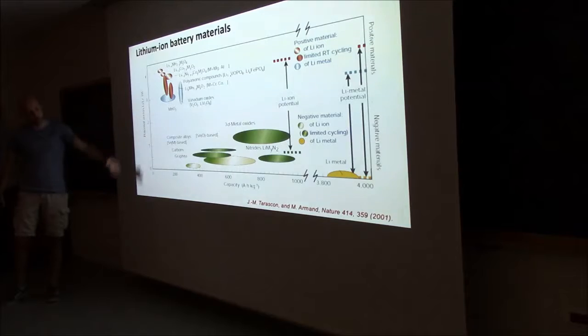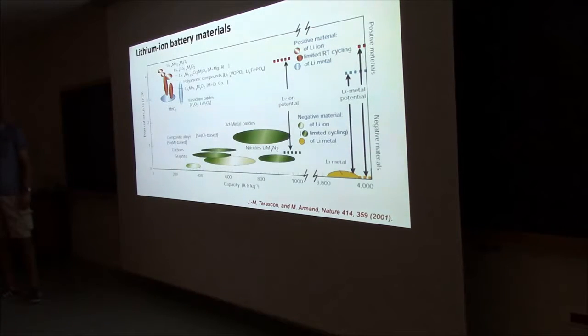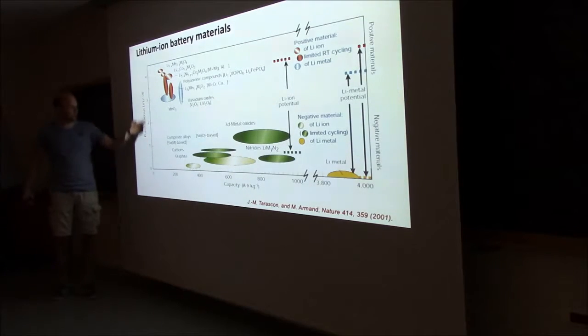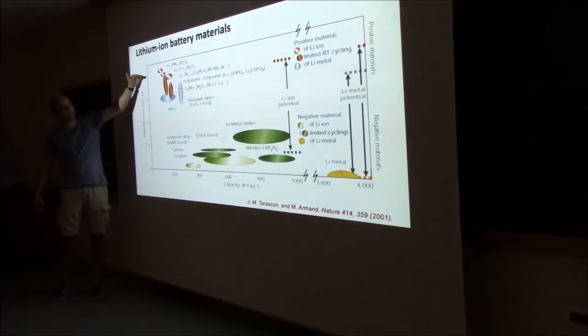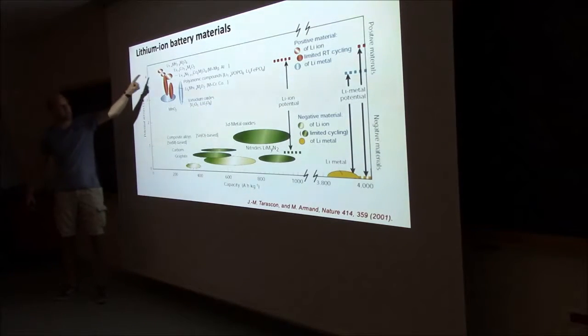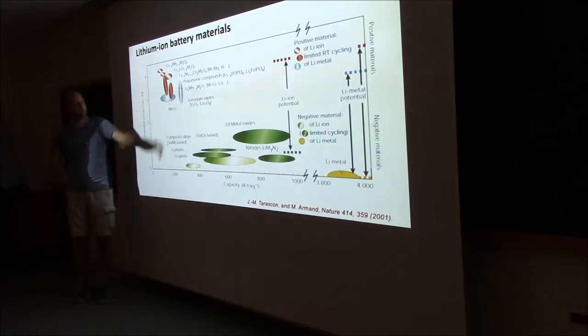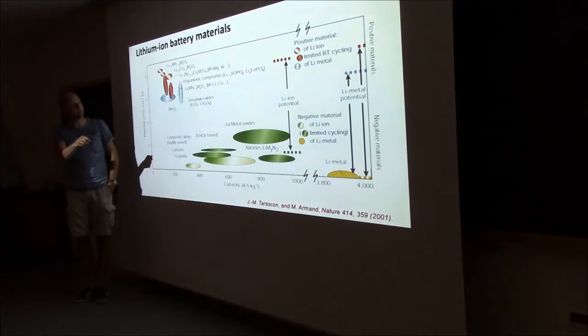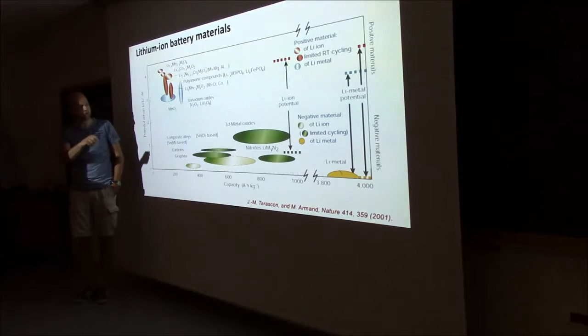This is an overview of, let's say, the most important components. You have the cathode side, the anode side. Here you can see the potential against lithium. So on the top, around 4 volts, that's where the cathode materials are. That's where you see a bunch of the oxides. So here, lithium cobalt oxide, maybe you can put in some other elements, lithium manganese oxide, lithium cobalt oxide with also some nickel, all kinds of variants. Vanadium oxide is over here, manganese oxide. So these are the cathodes.